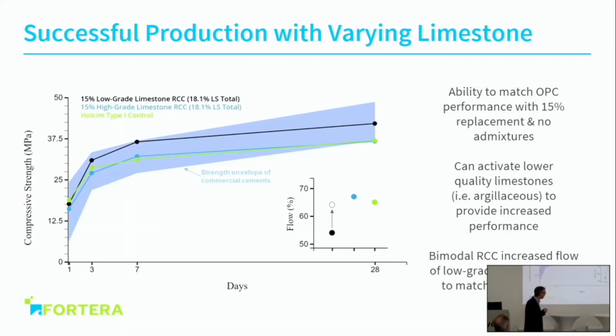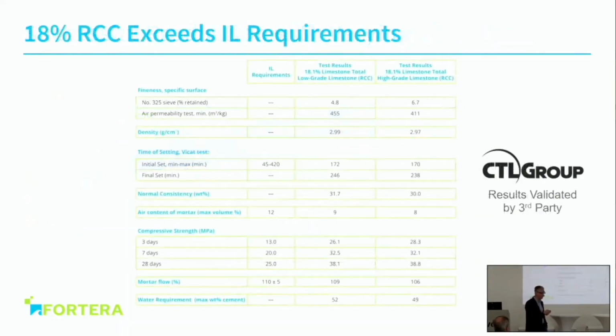So we learned in this process that using low-grade limestone could be even better for us than using a high-grade limestone. And what we also experienced is with this low-grade limestone, we first had a flow of the mortar below what we had with the other one. So we had to work on the particle size, to blend the particle size in order to fix that, which was also a good learning for us. So these are the results by a third party, so it will be in the presentation. I won't go into the details.